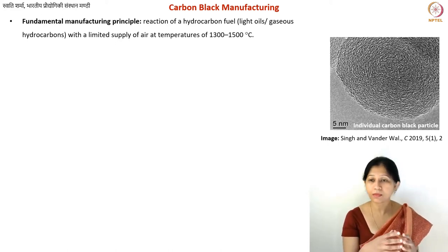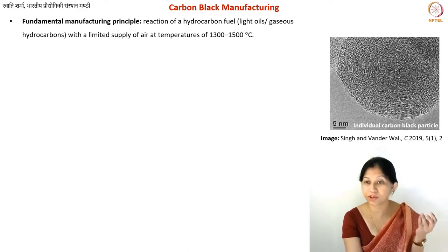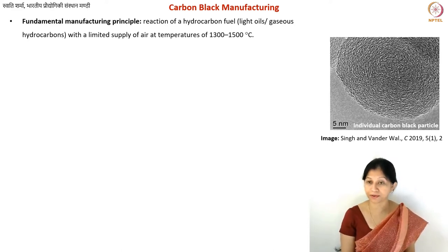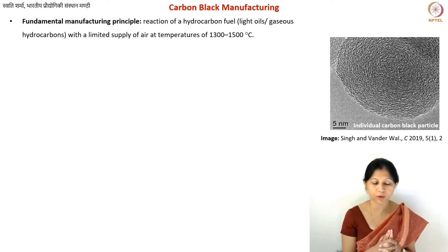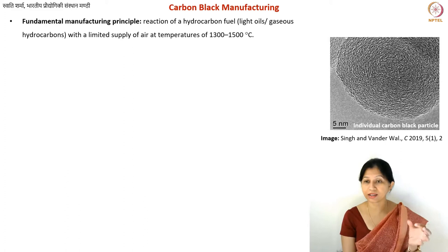We talked about diffusion flames and premixed flames earlier. Soot formation was the motivation — people realized that volatile and gaseous hydrocarbons can yield solid carbon particles when temperatures are high enough. The question is whether the decomposition is purely thermal — pyrolysis — or thermo-oxidative. We use the term combustion when you have excess oxygen, but in this case we do not have excess oxygen, so we call it thermo-oxidative decomposition.